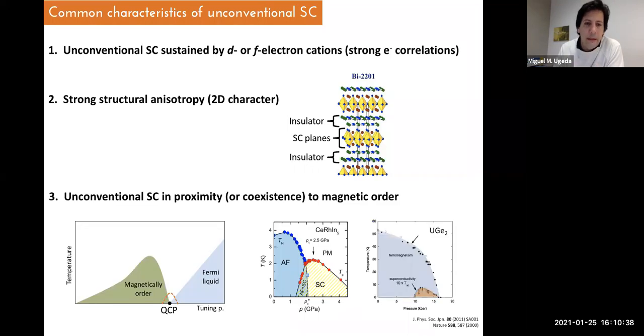And the third common characteristic is that in general, these materials show superconductivity quite close to magnetically ordered phases. In general, they develop around what are called quantum critical points. And the reason is because at these points, the fluctuations are quite high, because at this point you are close to, or in the vicinity of, a second order phase transition. So magnetic phases are second order phase transitions. So quantum fluctuations are quite high here, and superconductivity develops.